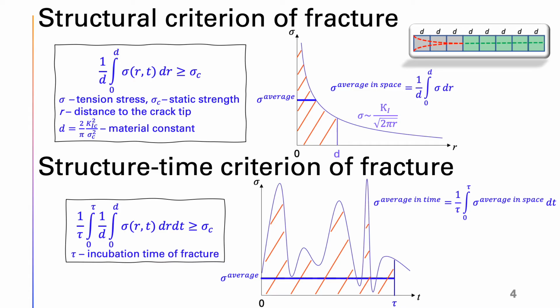As was already mentioned, the classical approach is not able to describe the effect of dynamic crack initiation. So, in this work, a different approach was used, the structure-time fracture criterion. An idea of the structural criterion is that there is a parameter such as a characteristic length. The crack propagation is a failure of the structural blocks of size d, one after another, starting from the crack tip. This approach states that there is a process zone of fracture, as opposed to the classical approach, which rejects it.